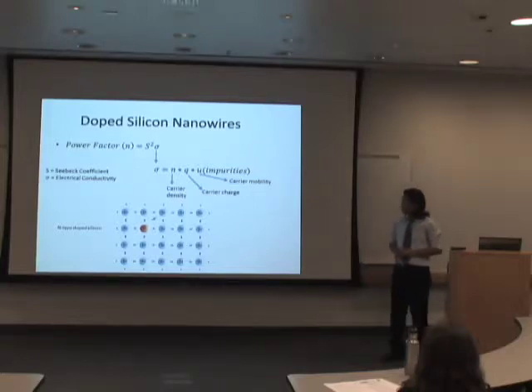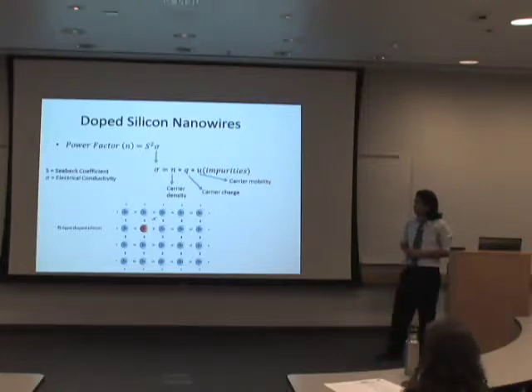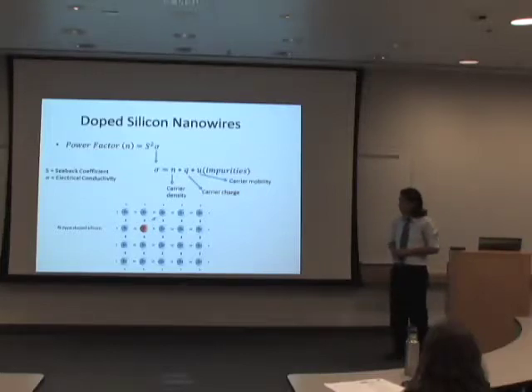To increase power factor, what people have tried is doping the silicon. As you see, the power factor is described as the Seebeck coefficient squared times electroconductivity. And the electroconductivity is related to how many carriers you have in the material. So by doping silicon and putting in carriers, you can increase its carrier density. However, at the same time, you decrease the mobility, as the mobility decreases as you keep putting impurities into the material. So you're limited somehow, somewhere, by this mobility, which after you put in so many impurities will take over, and electroconductivity will not increase anymore.